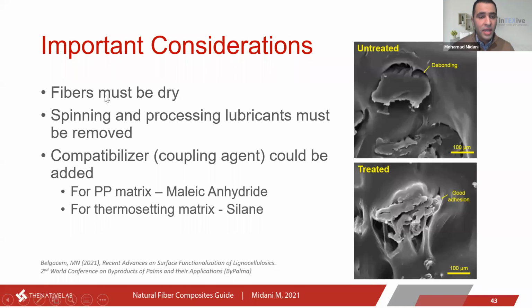Another important consideration is that if my reinforcement is not initially designed for this final application, so I'm buying, let's say, a jute fabric from any place, but it's not intentionally developed for composite application, probably it will include spinning and processing lubricants that need to be removed. And those lubricants act as a surface barrier. They create a barrier between the fiber surface and the matrix surface, so it significantly lowers the adhesion with the matrix, okay? So if this is the case, we need to wash or scour the fabrics, and we need to thoroughly dry them before using. Another important consideration is the use of compatibilizers, okay?